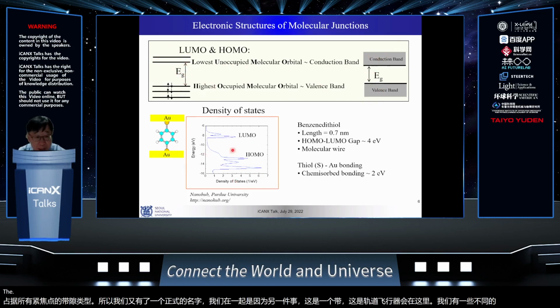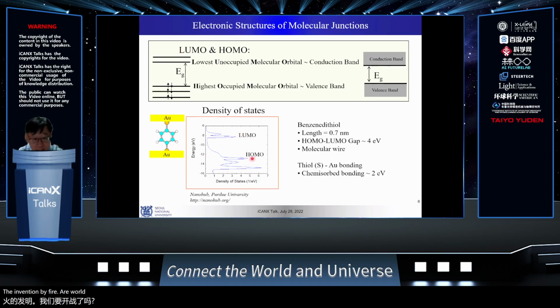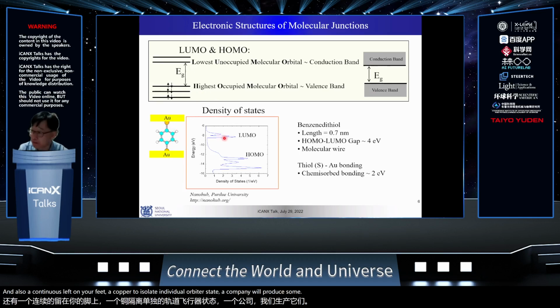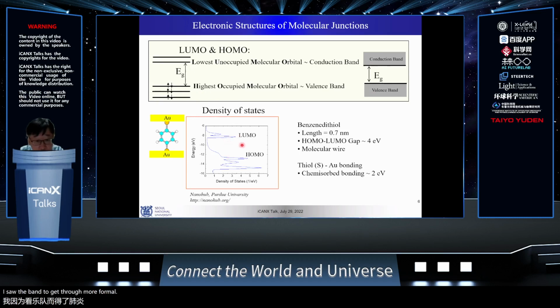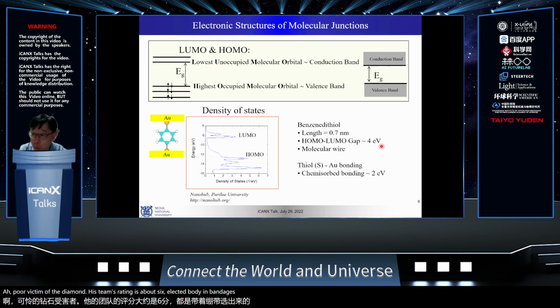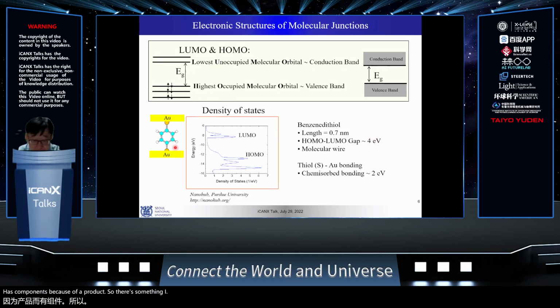Okay. So in benzene dithiol with gold contacts, it has a LUMO and HOMO. There's a broadening corresponding to each orbital. Broadening is due to a temperature effect, and also the continuous electron states of the electrodes coupling to the isolated individual orbital state will produce some broadening. The HOMO-LUMO gap is about 4 electron volts. In semiconductors, diamond is insulating with about a 6 electron volt band gap. So 4 electron volts is usually considered insulating, but the length is so small. Although the band gap is large, the length is so small that there will be a lot of current path component because of tunneling. That's something I will explain a bit.